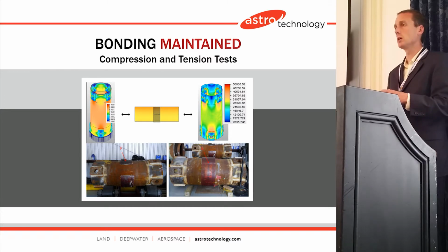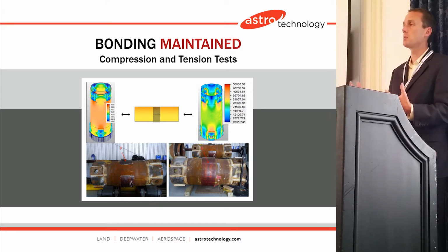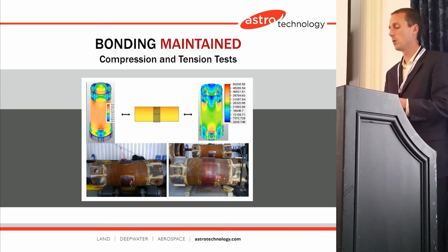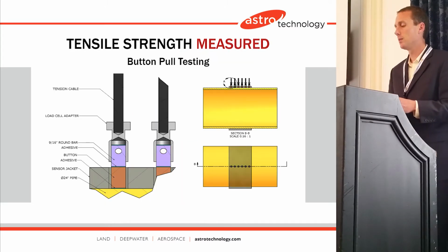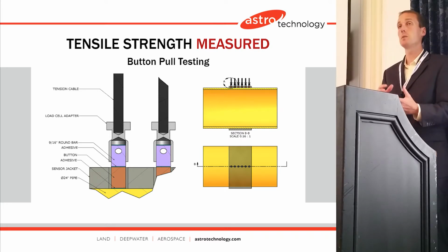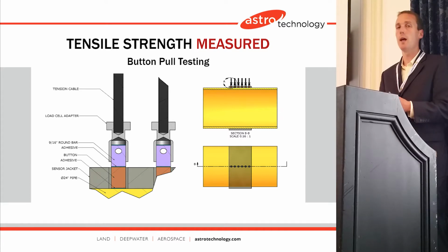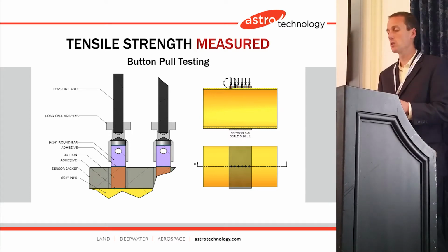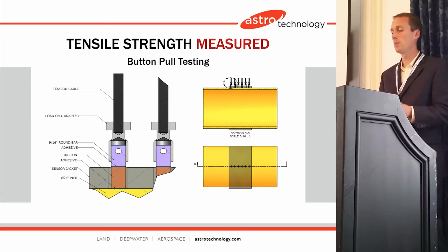We wanted to do the accelerated aging test, so we brought these samples up to 75% of yield strength for the steel that was used on the samples. Doing that, getting up to 75% of the yield strength with repeated cycles, allows us to have an accelerated aging test and be able to anticipate what is going to be the bonding life over a long period of time. So this is a mechanism that was developed specifically for this project at NASA. We used the NASA test facilities to do this validation with the support from the NASA engineers.